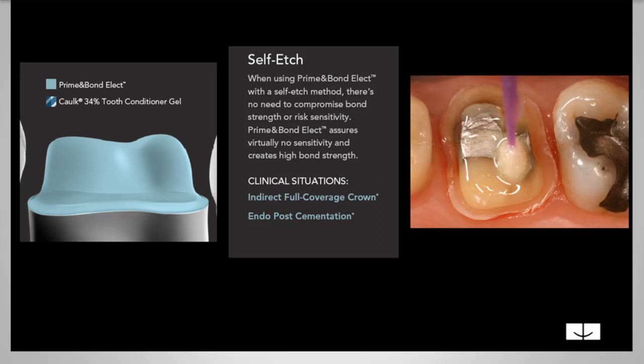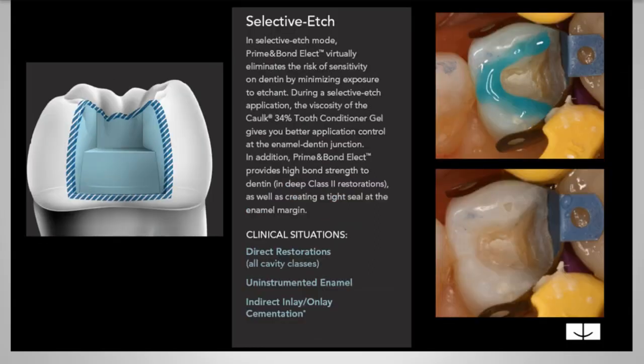Now the hard thing was, for so long I could never get my total etch material to sit right on the enamel edge without getting down into the box. And what used to happen before the universal bonding agents came out with the 6th generation, your 2-bottle self-etch, if you had any select etch, if you had any of that phosphoric acid etch get down onto the dentin, then it would compromise the bond of your self-etch systems. So what's happened with the universal bonding agents is that has been changed quite a bit. You can either do the total etch or the select etch, and it doesn't decrease the bond on the dentin. So that's a big advantage.